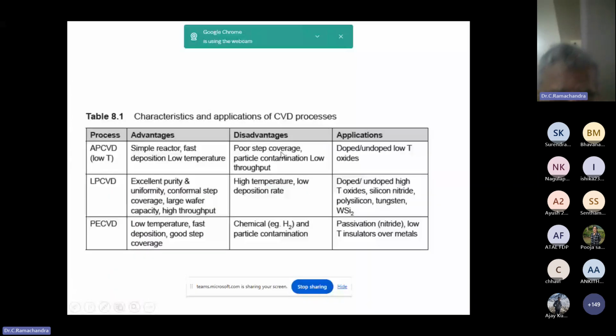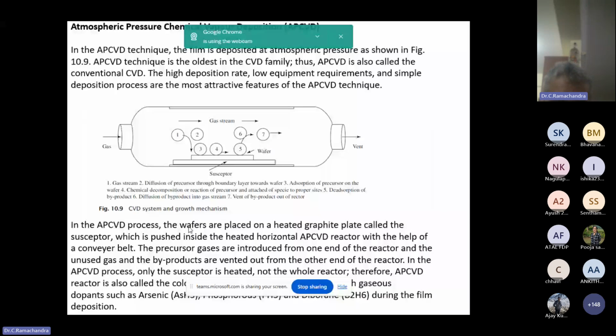So these are some of the comparisons. APCVD means atmospheric pressure: simple reactor, fast, but poor step coverage. Then LPCVD has excellent purity and uniformity, but high temperature and low deposition rate. PECVD, the biggest advantage is low temperature. If the temperature in normal CVD is 700 degrees, here it can be reduced to 300 degrees also. And it is a very big advantage from the production point of view. So you can see the simple configuration. There is a gas inlet, there is a gas stream, then after reaction that gas will be exhausted out. It's a relatively very simple chamber.